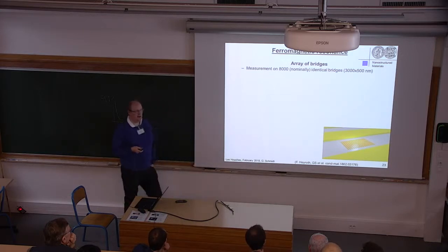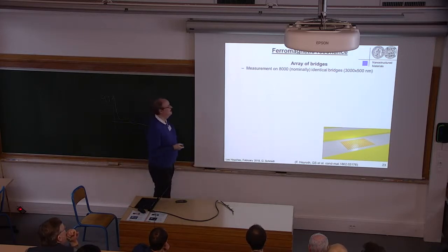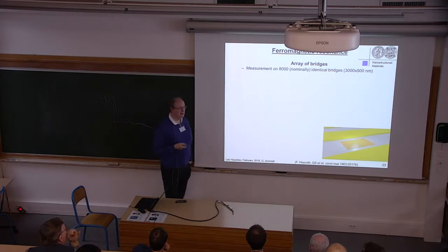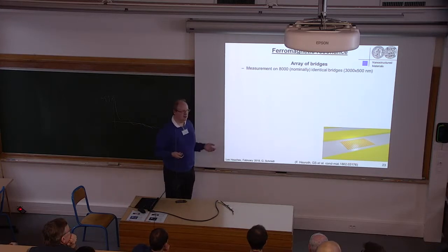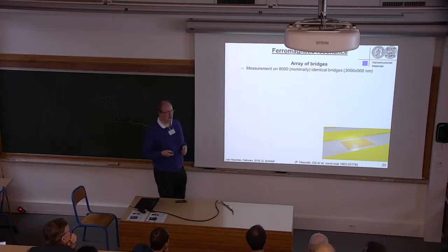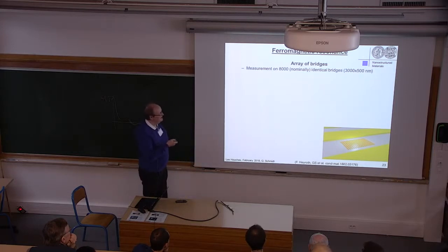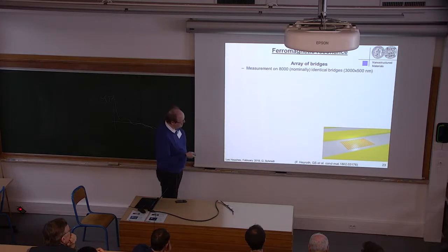And the first thing we did, because we didn't know what else to do, we just said we do ferromagnetic resonance using a coplanar waveguide. And as we cannot, or could not at that time, we still can't, do measurements on a single bridge, we had to do lots of bridges. So we made an array of 8,000 bridges, nominally identical, 3,000 by 500 nanometers, so 3 micron long, 500 nanometer wide. And this is in the gap of a coplanar waveguide.